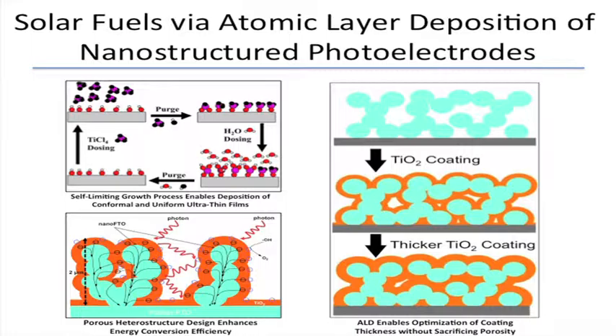We also look at solar fuels, meaning generating hydrogen and oxygen, and we do that with lots of different structures, but some of the most interesting, I think, are these nanoparticles of FTO covered with a very, very thin, like an atomically thin layer of oxide, which is TiO2 in this case, that allows us to get a much better conversion of the sunlight to the chemical.